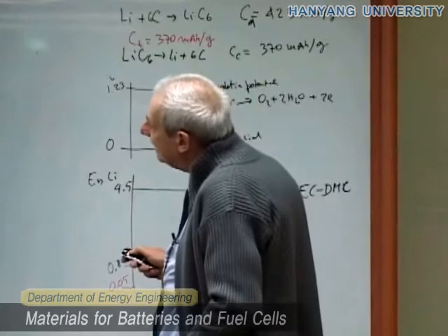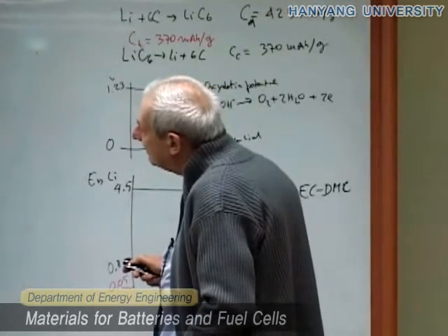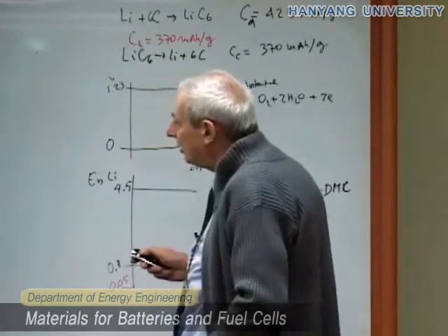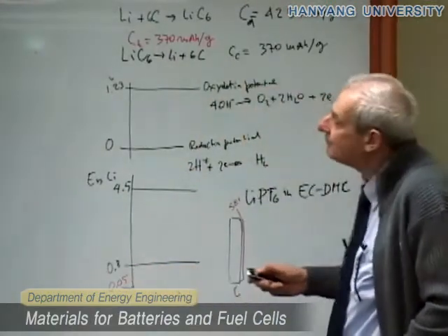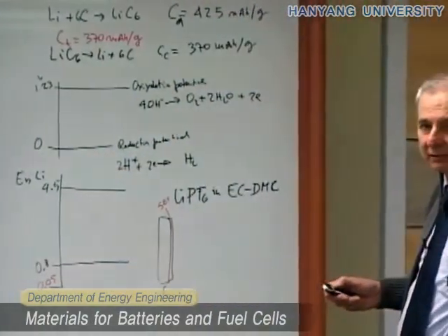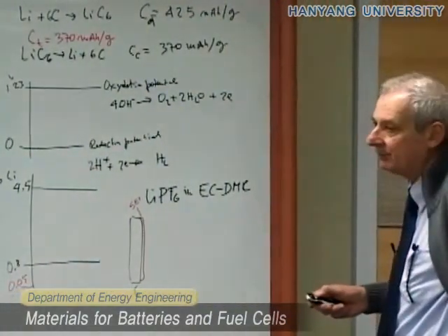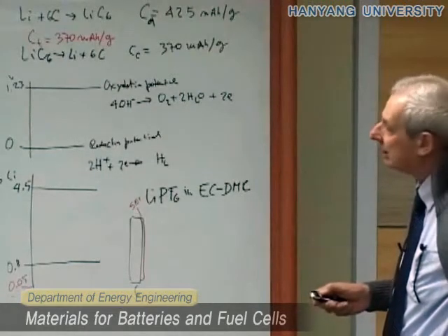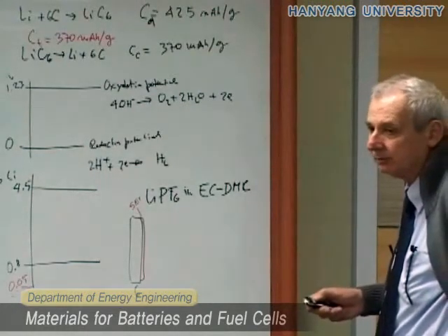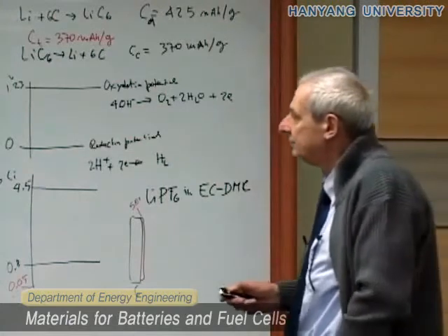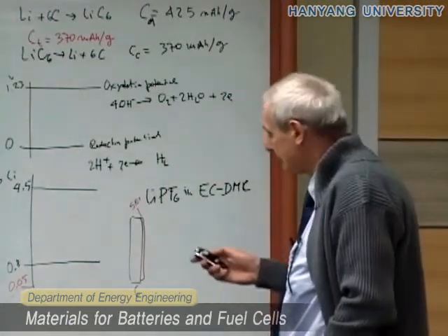So we have to take into account that in this particular case, and in all the cases where we have some film formation, the decomposition of the electrolyte, and so forth, we have some irreversible capacity, which, of course, is not good for application, but we have to deal with it.